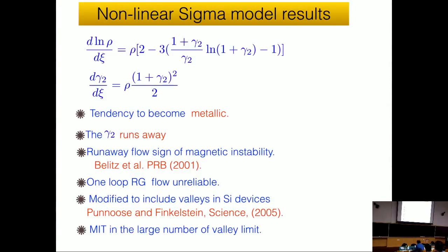interact, right? And what they found is that when you did the renormalization group equations, you essentially found this set of coupled differential equations. Here xi is something related to the temperature. It could be related to the length scale also, but in this case it's related to temperature. So what they found is that, of course, early on this 2 probably dominates, and then as you keep doing the RG, as you let t go to 0, this term essentially starts picking up, which means this term actually starts dominating. Then this essentially goes through a maximum, and then the resistance starts to decrease.